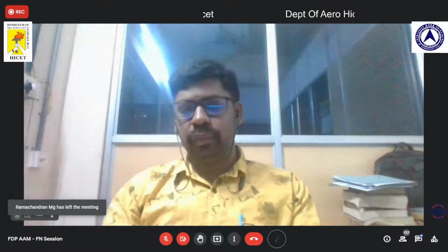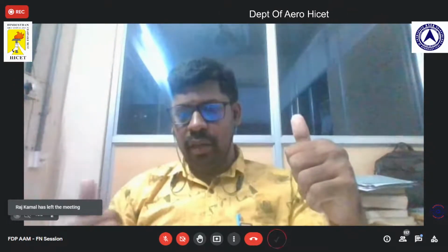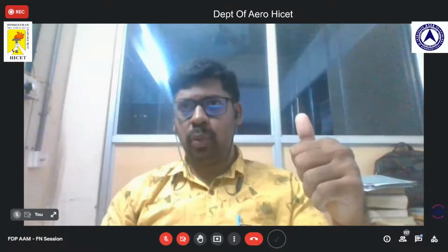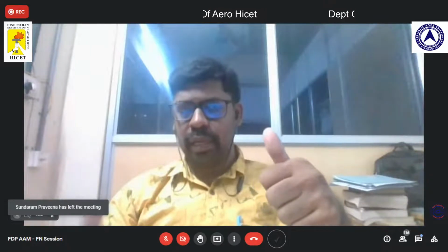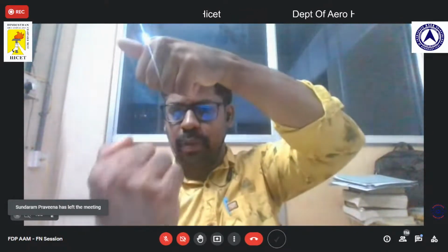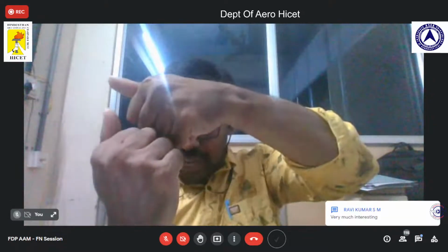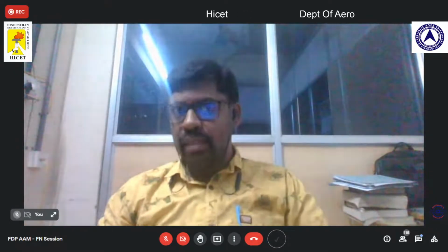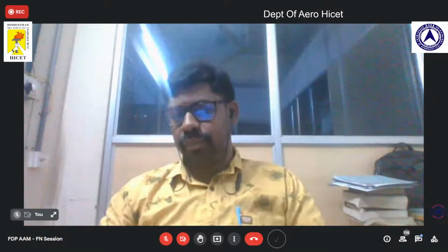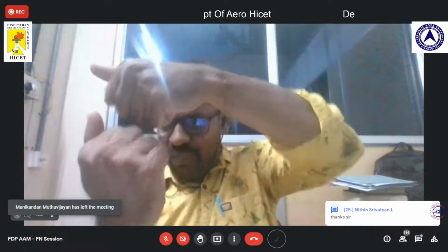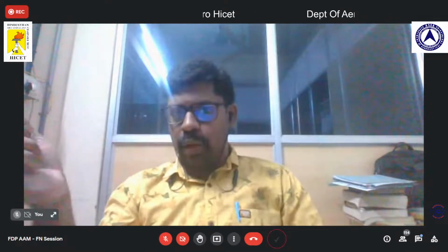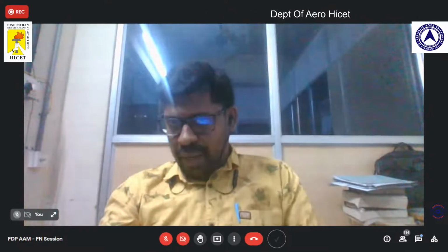Exactly. It is about the loading rate, how fast we are applying the load. In our typical testing to get the mechanical properties, we test at quasi-static loading, say 0.5 to 5 mm per minute. We pull the sample at a slow speed. But in high strain rate testing, the sample is loaded at high velocity. But why do we want to go for high strain rate? The reason is that, in general, materials are sensitive to strain rate. When I pull the sample at a low strain rate, I get some properties, but when I pull the sample at high velocity, I end up with other properties. So we need to understand its behavior at different strain rates, and also in practical applications.